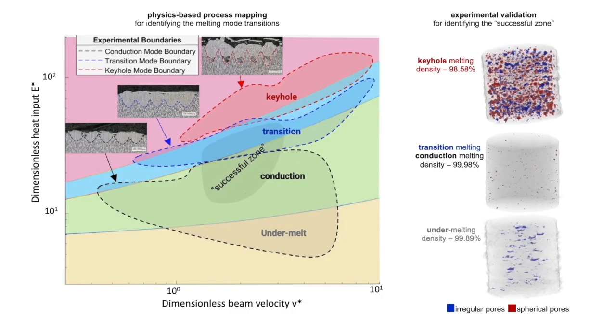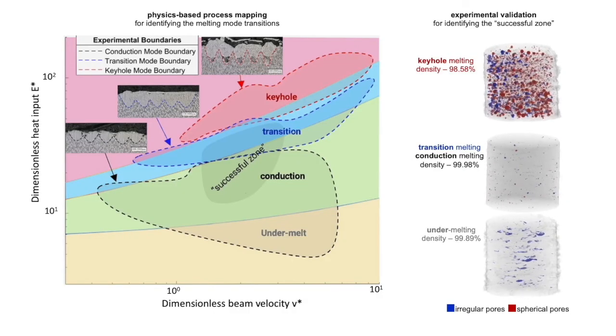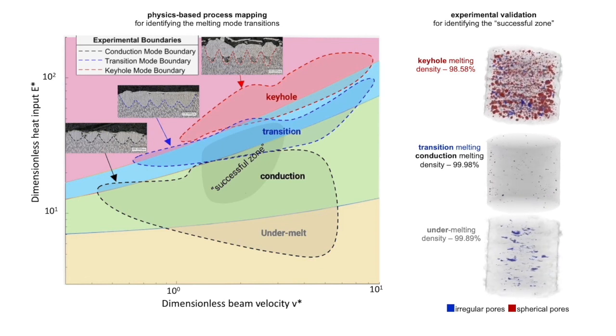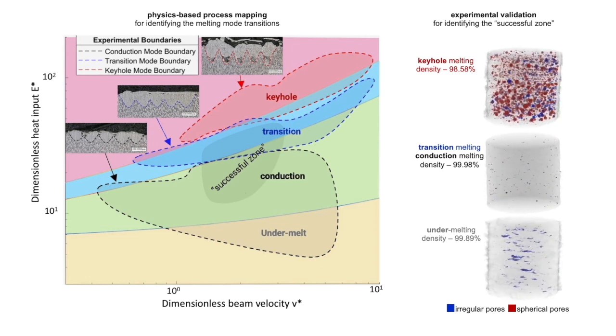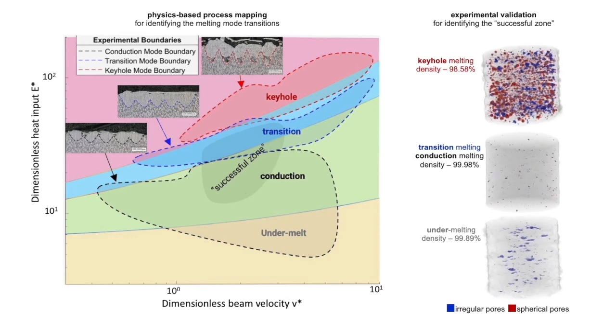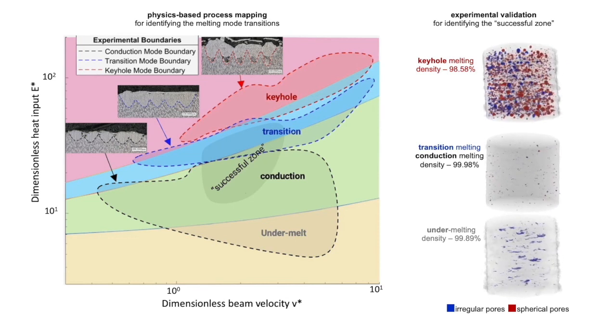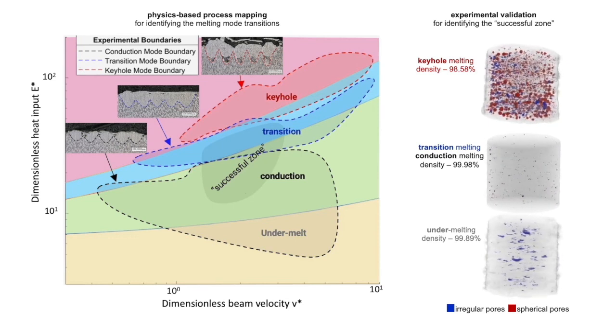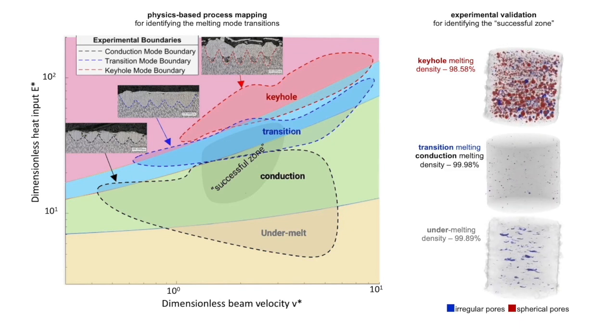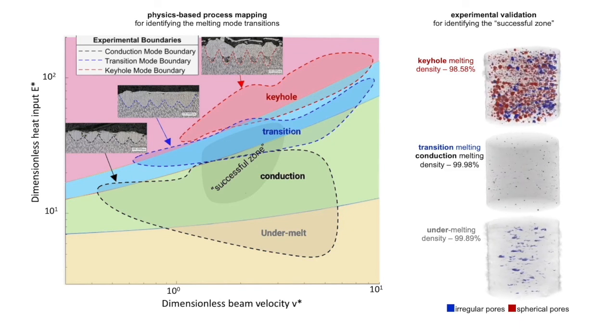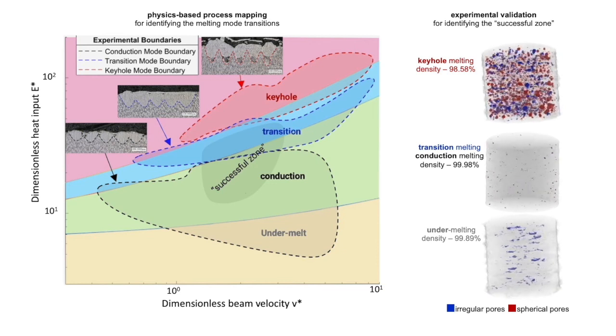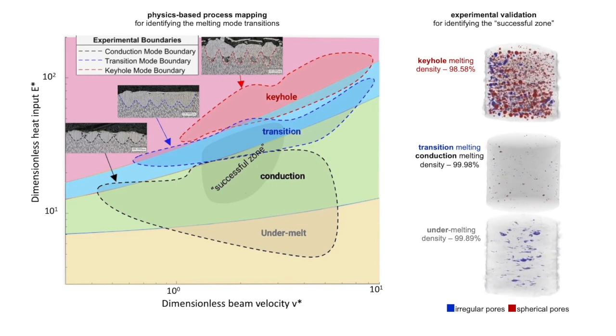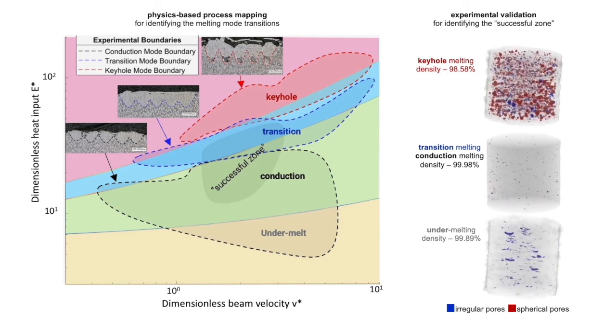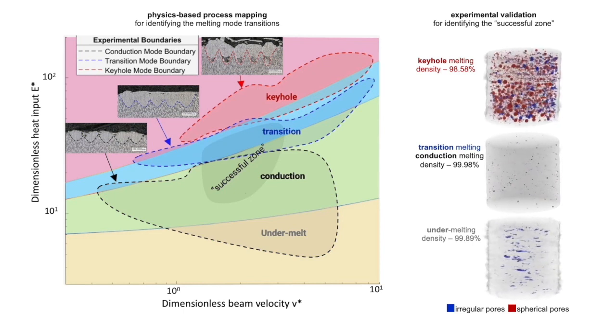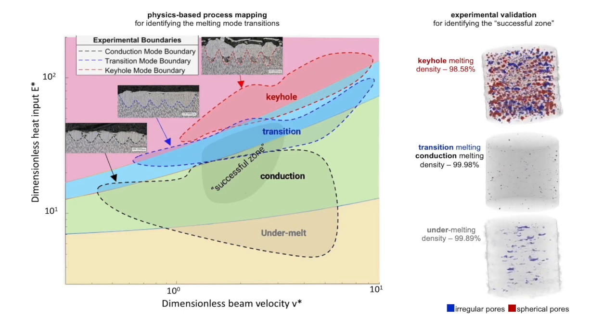We were able to complete the entire chain of process parameter development, printing, and testing components within a week. We wanted to prove to ourselves that fast process parameter development is possible and also enter in the USAF Manufacturing Olympics. The processing diagrams helped us narrow into stable conduction mode process parameters for Scalmalloy within 2 prints, wherein we were able to achieve densities of over 99.98%.